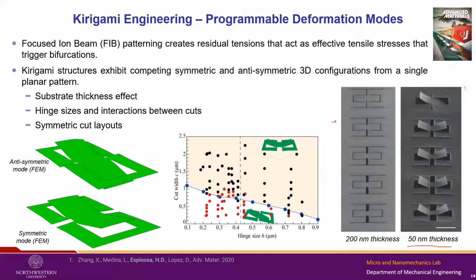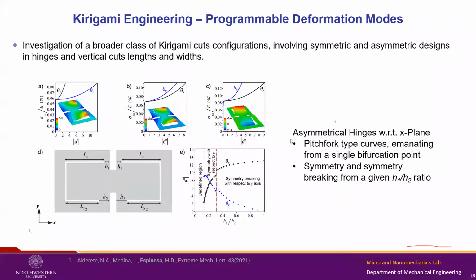And we were able to determine a kind of landscape where, based on the hinge size and the cut width parameters, which were the only parameters that we were changing, we were able to observe two different landscapes, as I said, an antisymmetric and a symmetric mode. We took this work a bit further, and instead of just studying purely symmetric patterns in all directions, we started playing around with other parameters, and some very interesting things showed up.